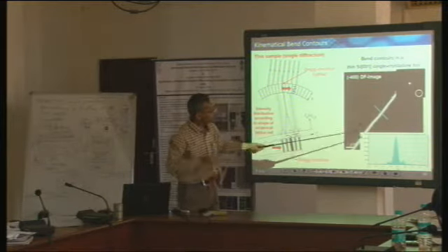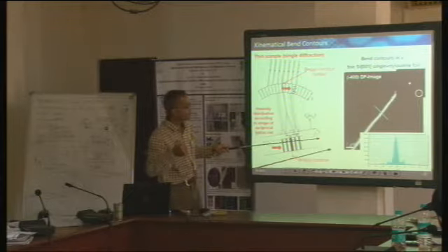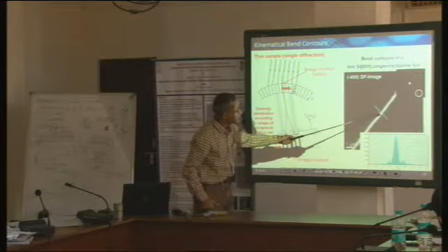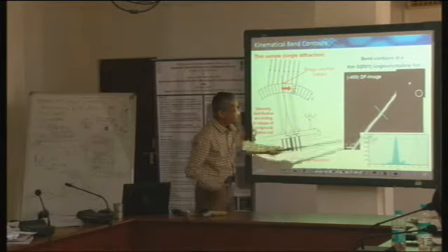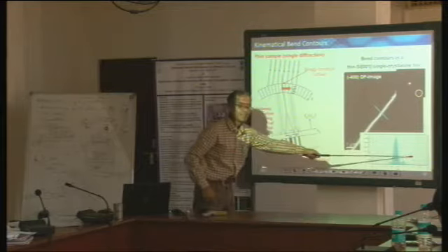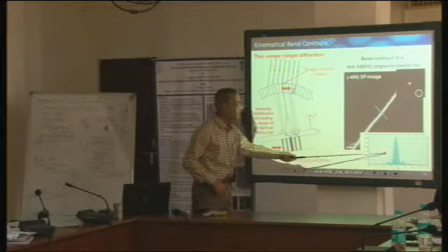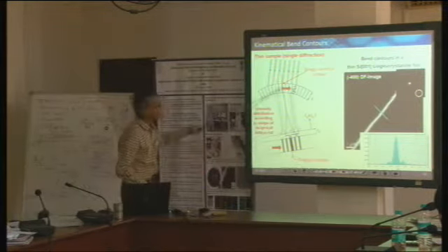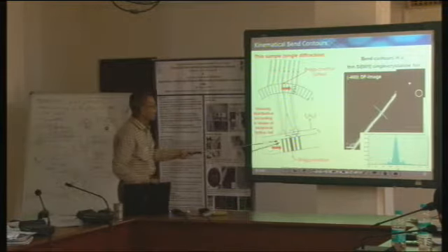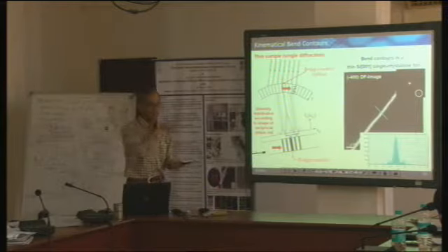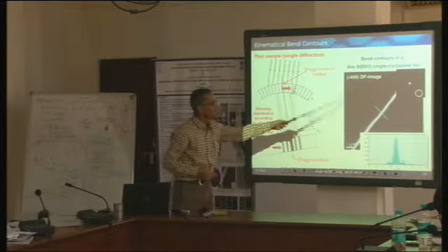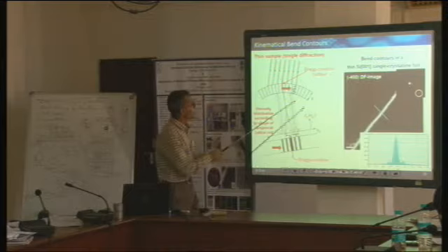This is the central maxima, but there are also side maxima. This is an experimental curve, and this is a calculation from that equation, and they match reasonably. At least I am able to understand this behavior here.